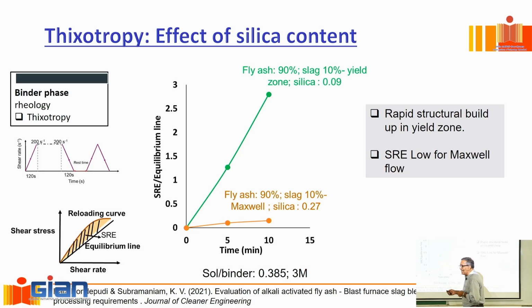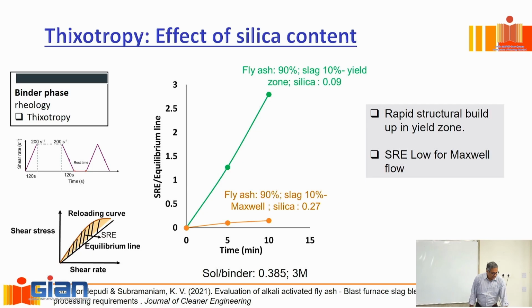Then this is rest time that you have is the time that the layer is sitting idle before the next layer comes on. Now, before the next layer comes on, I expect that the structuration that's happening, that should be rapid enough that it can take the next layer on, isn't it? If I was to print with this fellow, what's happening? It's hardly structurating. So if I put the next layer on it, it'll simply lose its shape and even collapse. And when does that behavior change? Look at the silica content. This is with a very low silica content. This is when I start increasing the silica content. Now the question is, then why not keep the silica content at low value? Strength. This is what gives me the higher strength. So I have to add silica for strength, but the minute I do it, I start losing structuration. Okay.